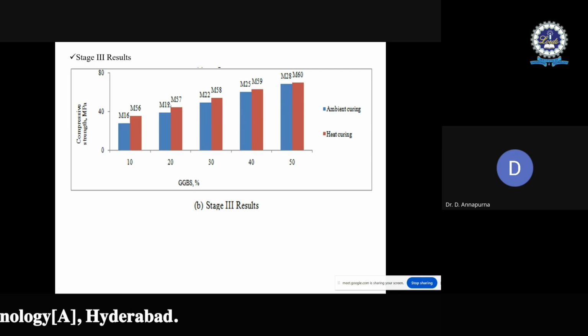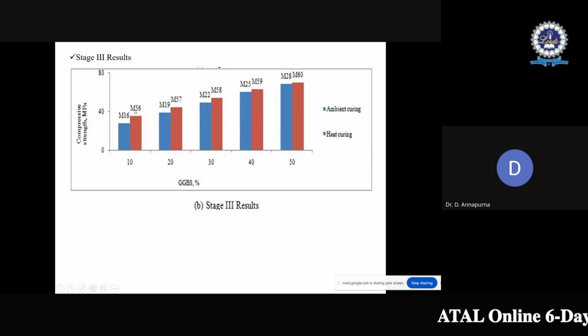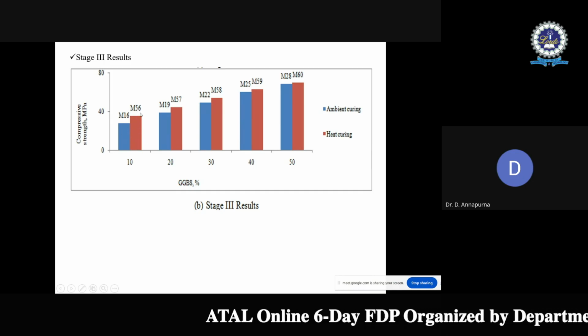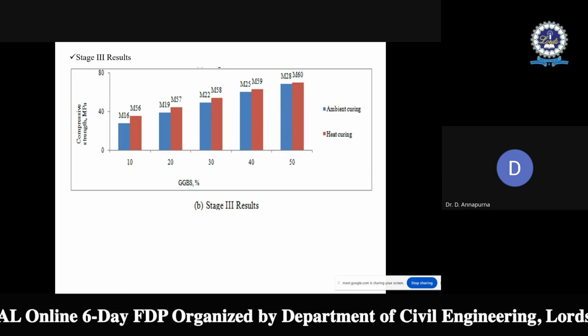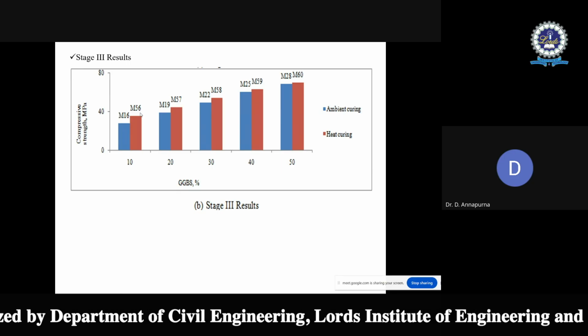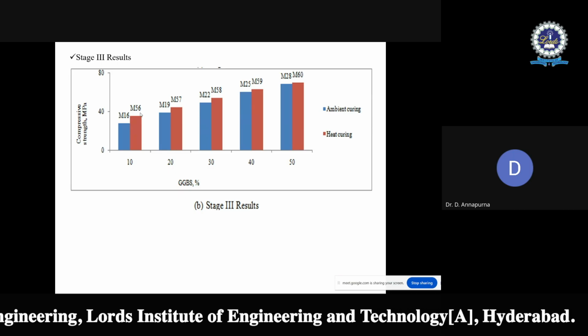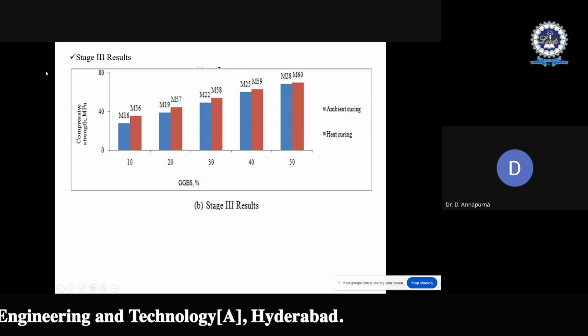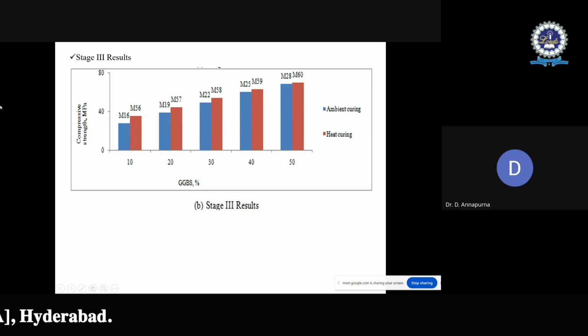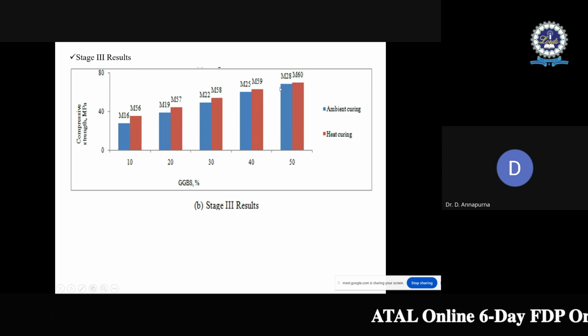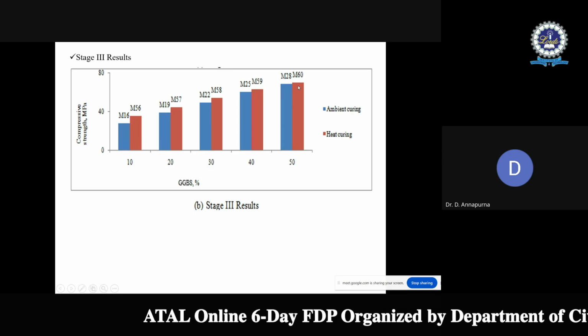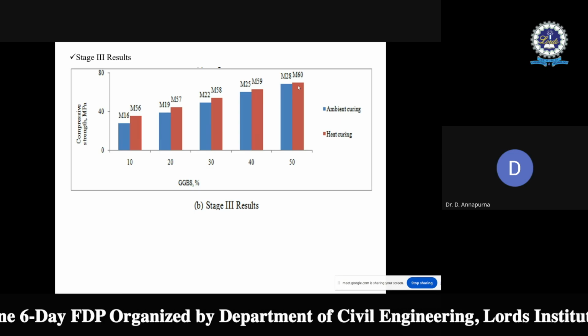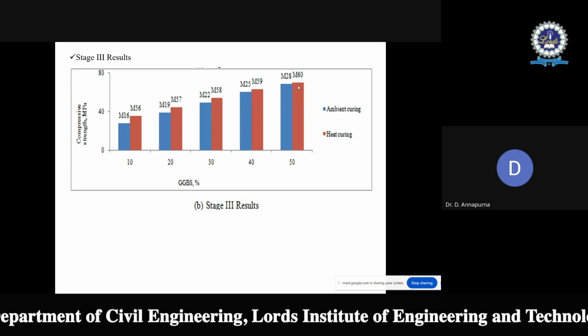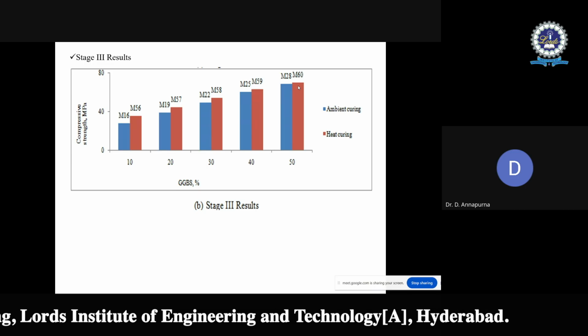As heat curing is done on the geopolymer concrete specimens, it shows improvement in the compressive strength. Around 10 to 15% improvement of compressive strength is observed. But at the same time, when the GGBS dosage is increased, the difference between ambient curing and heat curing is reduced. So almost the same amount of compressive strength is observed between the ambient curing samples and heat curing samples.